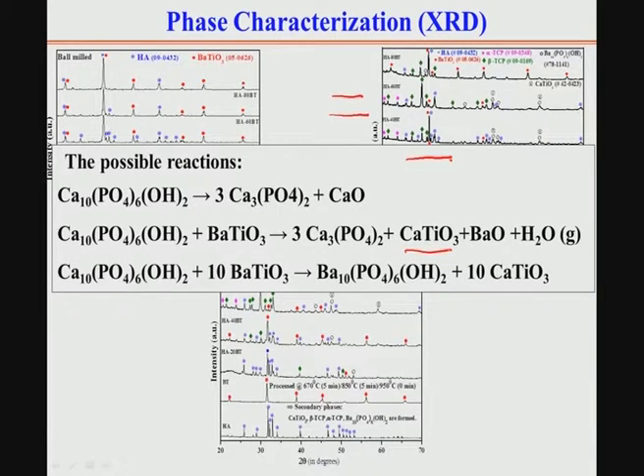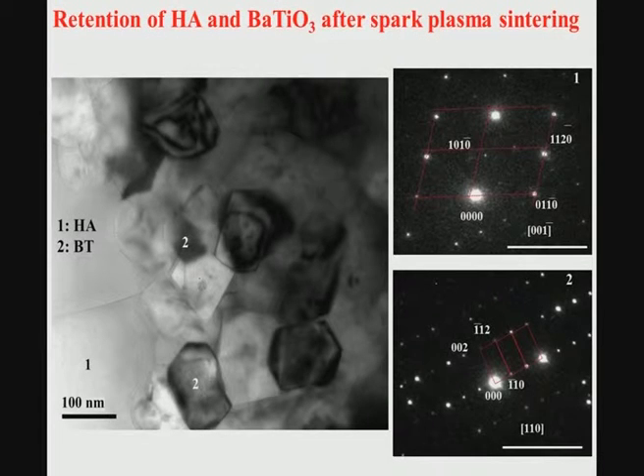So, therefore, we have proposed these kinds of thermodynamic reactions where hydroxyapatite can dissociate to calcium phosphate, and hydroxyapatite can react with barium titanate to form calcium phosphate, calcium titanate and barium oxide, and then calcium phosphate also can react with barium titanate. The beauty of this reaction is that you can see it forms Ba10(PO4)6(OH)2. That means barium will simply replace the calcium, and as a result calcium also will replace barium in barium titanate to form calcium titanate. So, this is kind of an exchange reaction that can potentially take place during sintering.